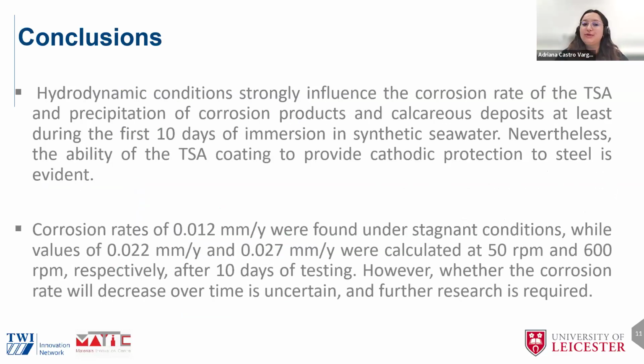So as conclusions, it's clear that hydrodynamic conditions strongly influence the corrosion rate of the TSA and also the precipitation of calcareous products and corrosion products, at least during the 10 days of immersion. Nevertheless, the ability of TSA to provide cathodic protection to steel is quite evident. We report in these experiments low corrosion rates under stagnant conditions, around 0.012 millimeters per year. But of course, they are higher with 50 and 600 RPM.